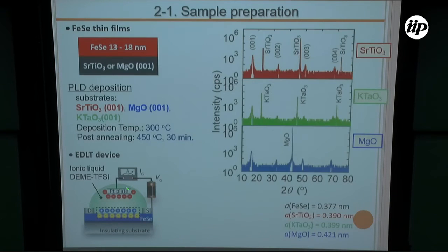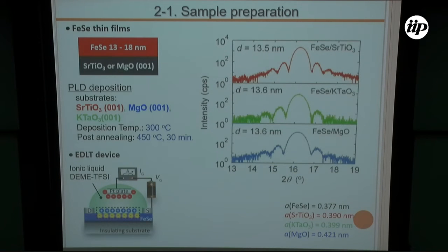Samples in this work are prepared by the PLD deposition method on strontium titanate, MgO and potassium tantalate substrates, followed by post-annealing in a vacuum. As shown in these X-ray diffraction patterns, we can obtain completely c-axis oriented films for all the substrates. And as shown in this magnified figure around the 001 peaks, we can obtain clear Laue fringes, implying that our thin film is very flat.